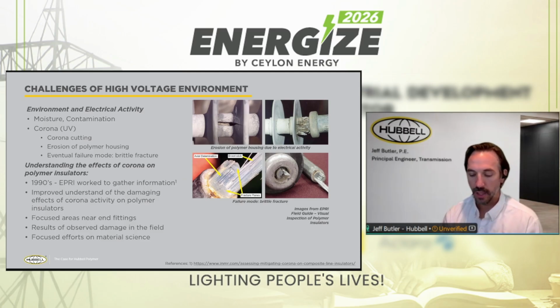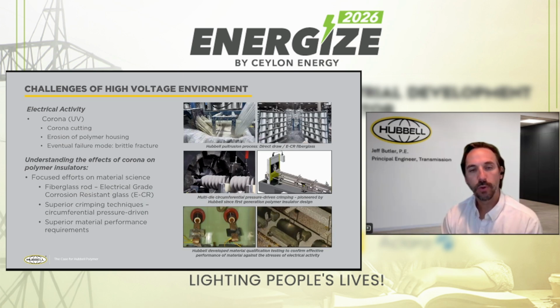When insulators were first introduced, a lot of these stresses were not well understood. So in the 1990s, an organization called EPRI, the Electric Power Research Institute, based in the United States, supported by STRI, the Swedish Technical Research Institute, combined to explore where there were issues occurring with polymer insulators out in the field, where they were experiencing premature failure. In their investigation, they found the electrical activity was degrading the insulators primarily at the interface of the end fitting, the rod and the rubber. Where all three of those interfaces come together, as shown in the pictures, that's where they were seeing the primary number of failures. That's not to say that all polymer insulators were having issues, but those that were had it concentrated in this area. That led them to understand certain aspects of the environment for the insulator that were not previously well understood.